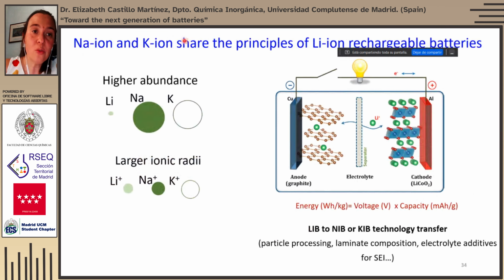So sodium and potassium ion batteries, which are monovalent as is lithium ion, do share in principle most of the same principles of operation of rechargeable lithium ion. And indeed, many of the processing parameters, like particle processing, how to make secondary particles, the composition of the laminates, where besides the active material you have a conducting carbon and you have a binder, the additives that are used in the electrolyte for the formation of the solid electrolyte interface, many of these parameters can be transferred from the lithium ion battery to the sodium and potassium ion battery. However, each of these chemistries has its specific issues. I mean, they are different. The abundance we've seen is 1,000 times more than lithium, but also the ionic radii change and its reactivity as well.